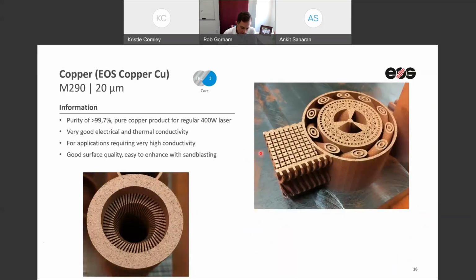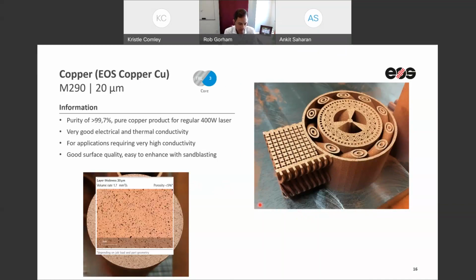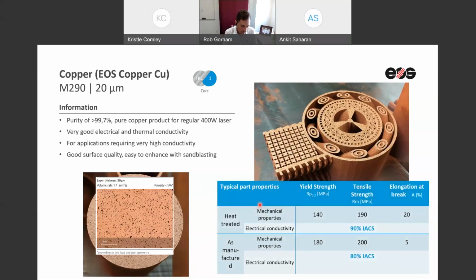However, as many of you might know, on the EOS side, a lot of people have an M290, which is not equipped with a kilowatt laser, but is equipped with a 400 watt laser. So to deal with that issue, we came up with a 99.7% pure copper, which is very good, again, for thermal conductivity. You can get very near to IACS values and also quite good surface finish. However, in terms of density, you're still talking about 95%, which is essentially the result of a lower power laser here. And like I said, in terms of conductivity, you can get up to about 90%. So if that's your prime driver, and cost-wise, this still seems like a good application.